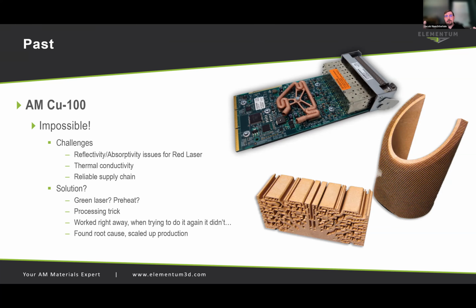Because it's a powder, when the laser interacts with the material, even if it reflects, it has multiple chances to absorb because it can reflect off the individual particles of the copper, which then allows us to melt the material, but you have to move the laser very, very slowly. So then it was uneconomical. So we ran into some issues right away with it being uneconomical to print, it leaving high porosity, and only being able to get to like 94, 95% dense with a print. And that just wasn't far enough.